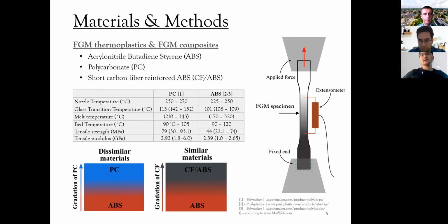Why did we choose ABS? Because ABS and polycarbonate are widely used, and their melting temperature and glass transition temperature allow us to fabricate these two materials in one mixing chamber. Actually, ABS is a very broad class of copolymers. It's an amorphous material. It doesn't have a true melting point, but according to MatWeb, as you see, the melting temperature varies from 210 to 343 degrees Celsius. And for polycarbonate, it varies from 170 to 320. Polycarbonate is an amorphous polymer as well, so it doesn't have a true melting point. Depending on the application, we can decide how to use these materials in our fabrication.